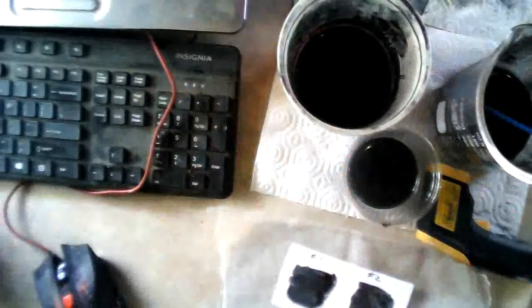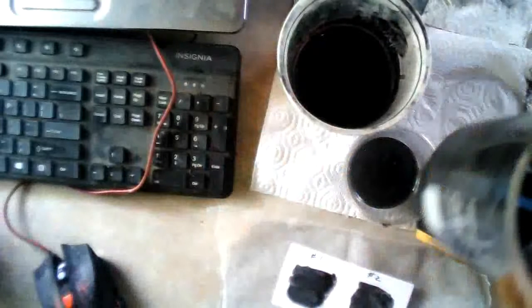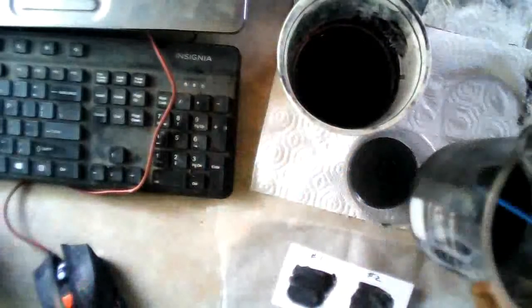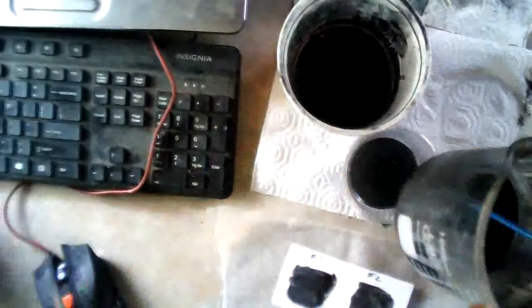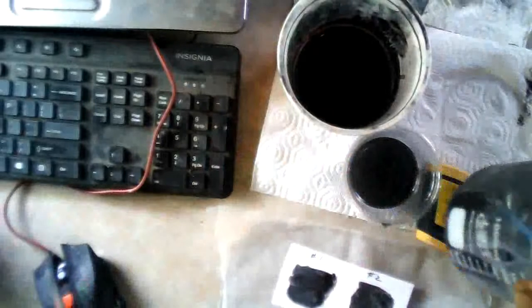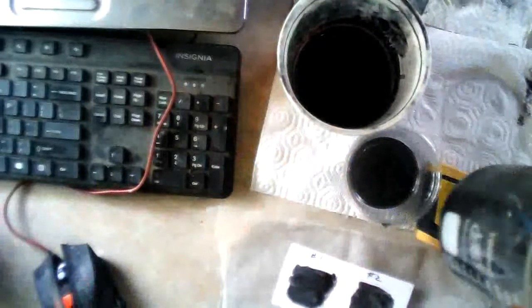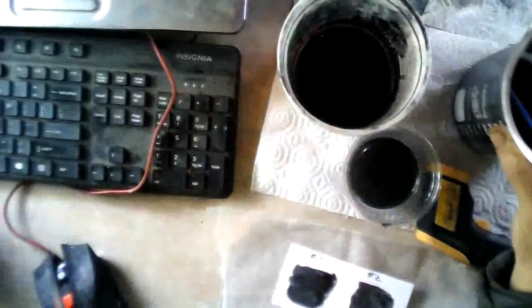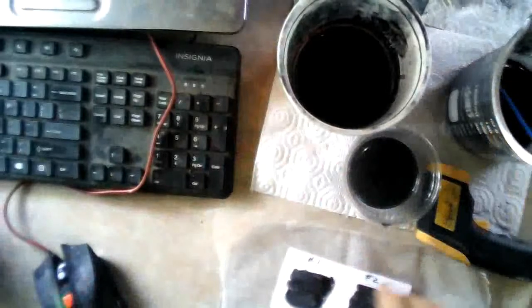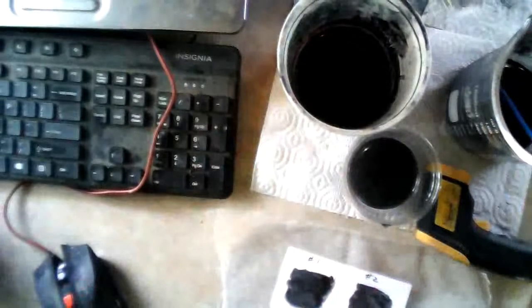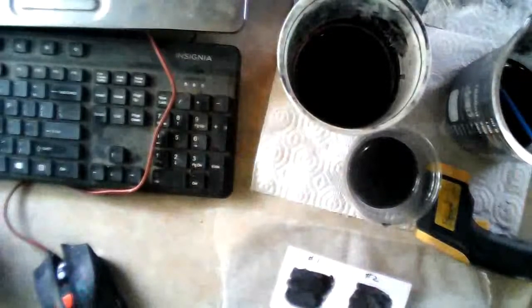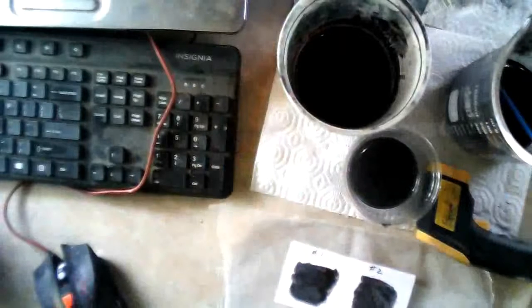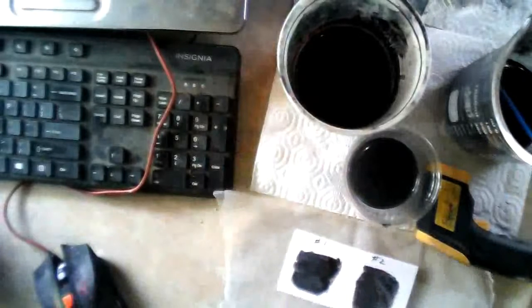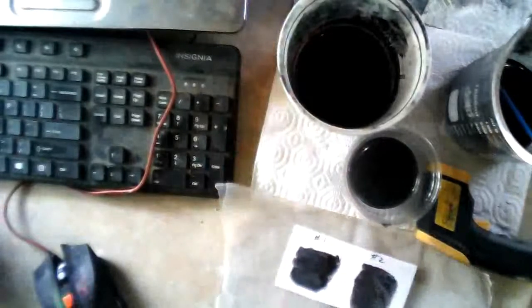I'll test it again after a while and see how long it stays in suspension. Now this is the new stuff right here that I've done, and I've stirred this on the magnetic stirrer for about 16 hours, and it's just straight sulfuric acid and graphite. And I've also painted both of these. This is number one on here, and I painted number two right here. I'm going to let it soak in and dry, and then I'll buff those surfaces and see what kind of resistance we get after that.